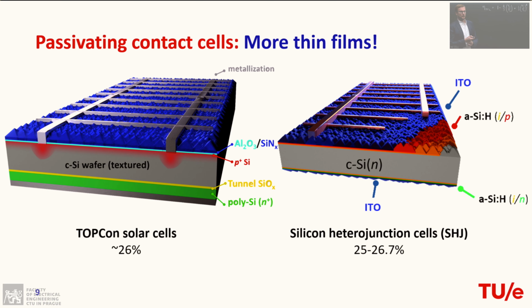So now, what do these passivating contact cells actually look like? We want to have basically full area coverage of your wafer. And then you see that everywhere in this whole design, it's all about making very thin films. You start with a very high quality wafer that you just buy, and then you texture it. And almost everything else is thin film fabrication. The TOPCon cell we already discussed on the previous slide, you see on the left here. Another structure that's also quite classical already since the 1990s is the so-called heterojunction cell, which is based on amorphous silicon. Here we first have an intermediate layer of intrinsic amorphous silicon, which is providing chemical passivation, and then doped amorphous silicon on top of that to provide carrier selectivity. So you might say that both of these are actually heterojunction devices. One of them is based on CVD of amorphous silicon, whereas the other one is a more high temperature process route.